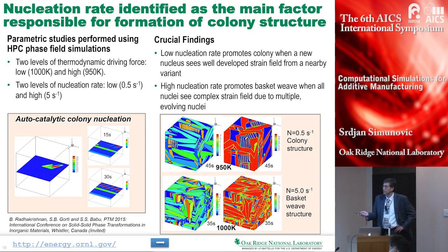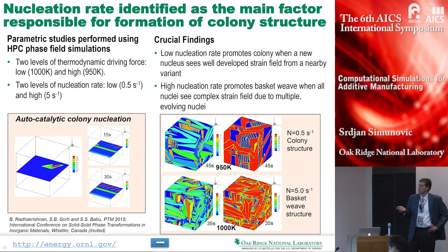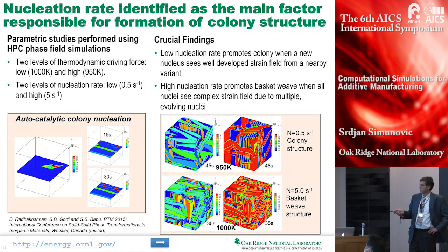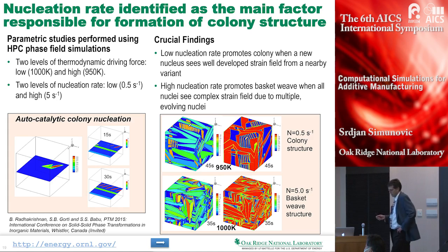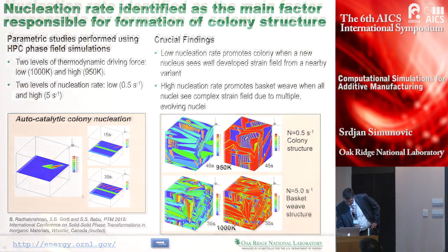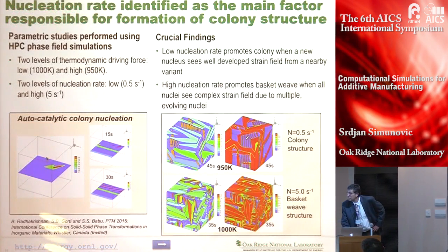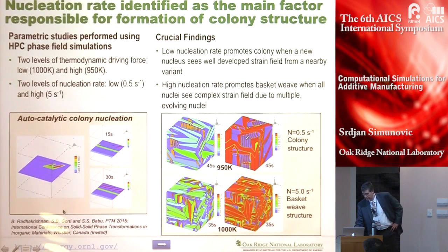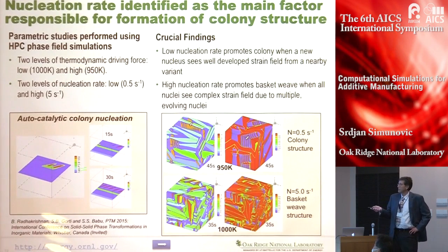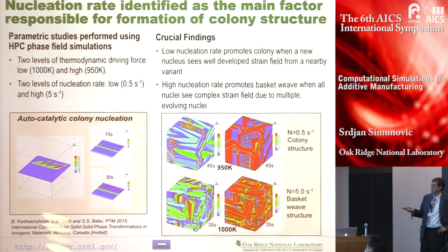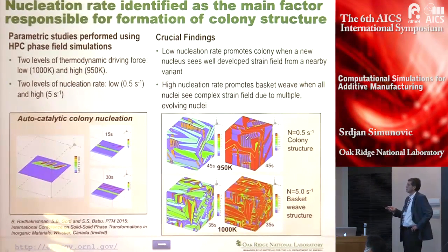So what we ended up doing is setting up a large number of high-performance computing phase field simulations that confirmed one of the assumptions in which way this structure forms. So this is the phase field triggering of this basket weave structure, as you can see, and the colony structure is driven by the lower thermodynamic force and also the lower nucleation rate.